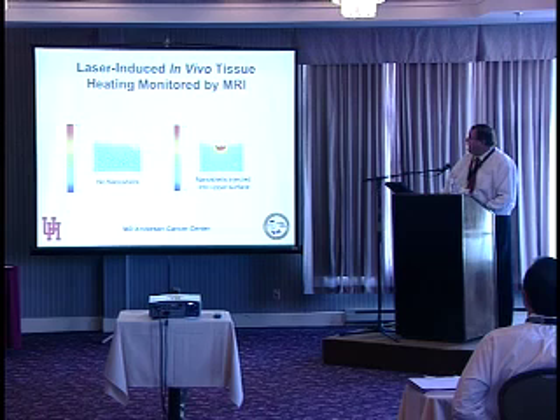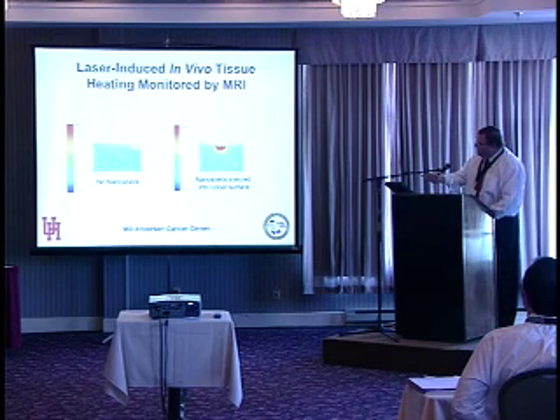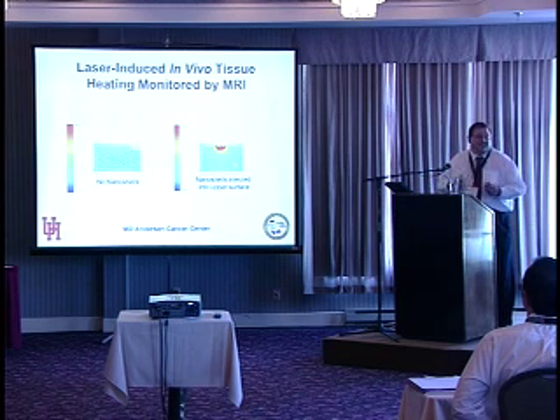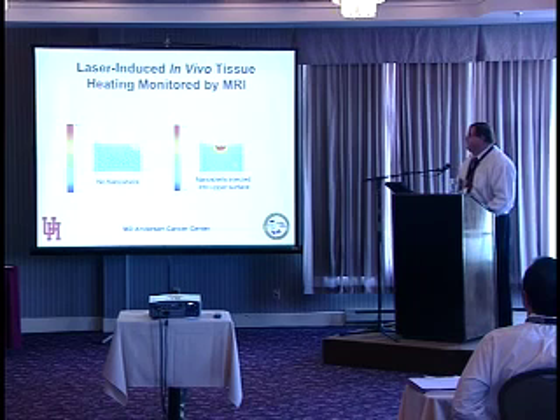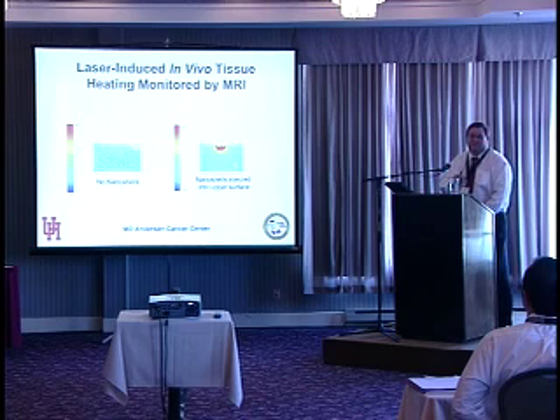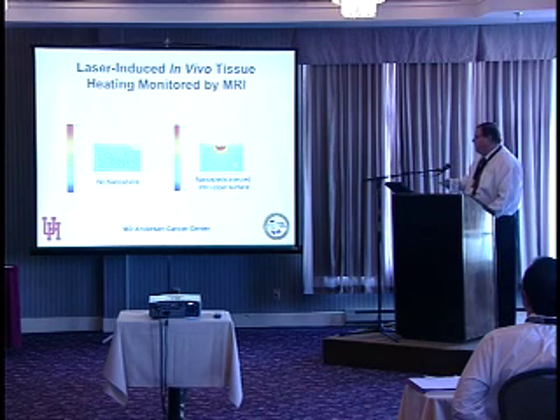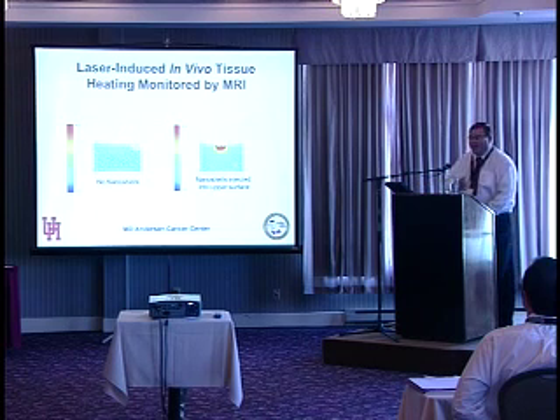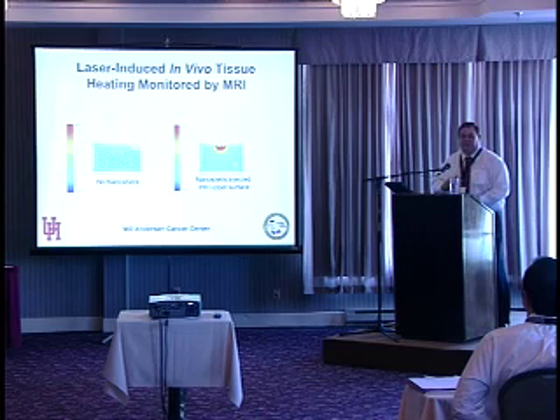targeting agent. In another experiment demonstrating the ability to deliver heat using nanoshells, and this is a very complicated and expensive experiment using magnetic resonance imaging. If you take a piece of tissue and you blast it with a near-infrared laser, basically nothing happens. The tissue doesn't change temperature, nothing goes on. But if you inject nanoshells just under the surface layer and then blast with a near-infrared laser, you can, using magnetic resonance imaging, monitor the heating of the tissue directly. And so that's a real fancy way of demonstrating it.